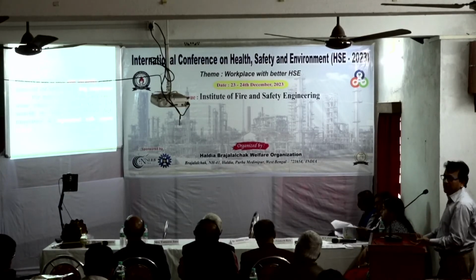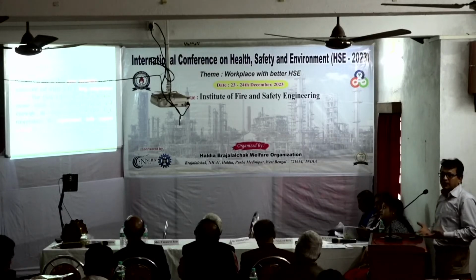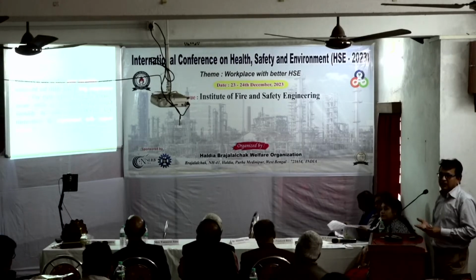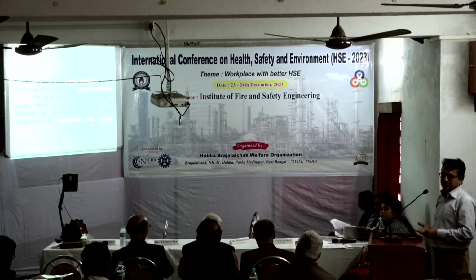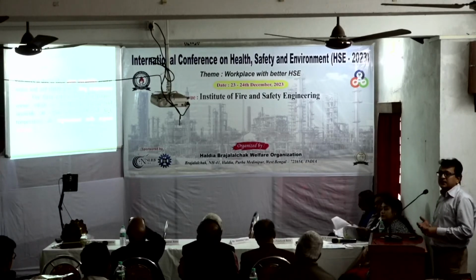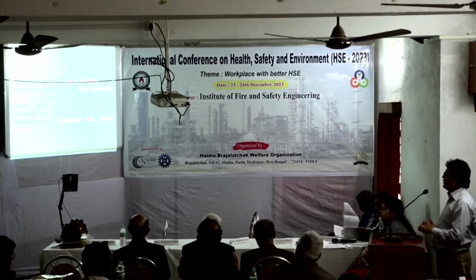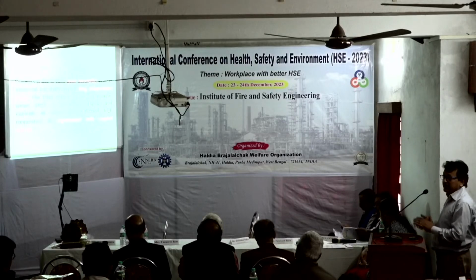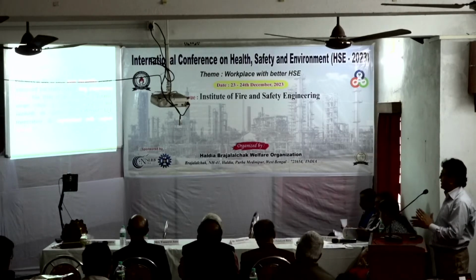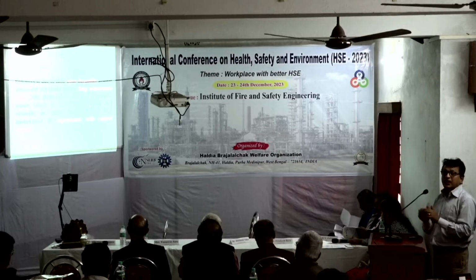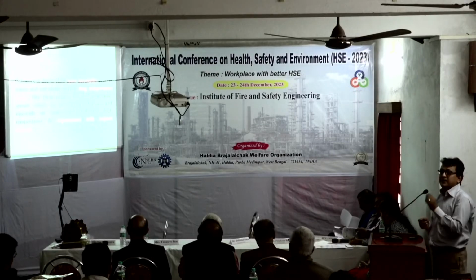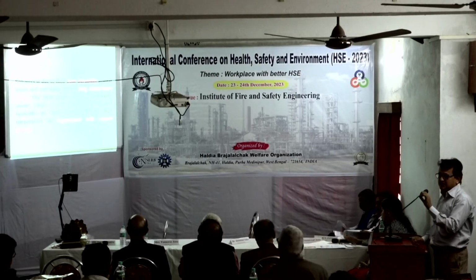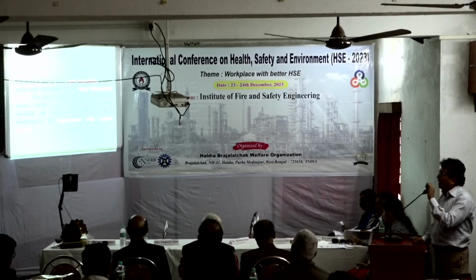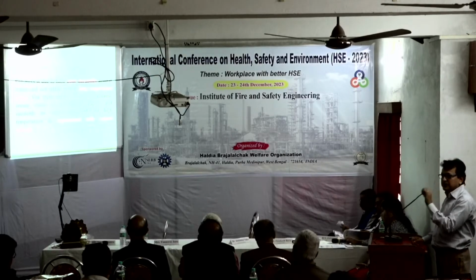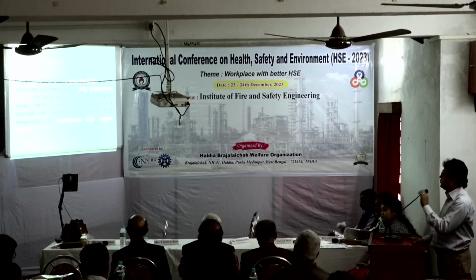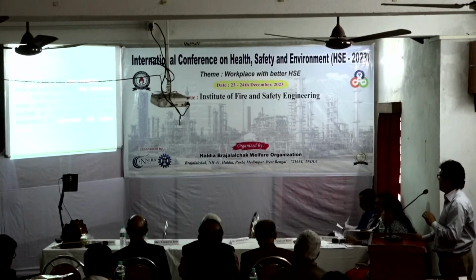Now the question: why ceramic? Why not polymer? Actually, polymer has two difficulties. First, it is easily degraded. Second is temperature stability. Polymer materials cannot be stable above 50 degrees centigrade. But there are special applications, which I will show in the application area, where the temperature is more than 100 or 200 degrees centigrade. In those temperature regions, a moisture sensor is required and there is no option to use a polymer sensor. A special ceramic based sensor is required. That is why we work on ceramic based sensors.